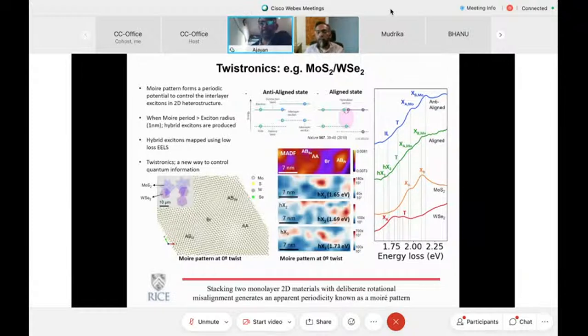And again, these are very difficult to characterize sometimes because, first of all, you need to have single crystal layers to understand how exactly these things go. And secondly, the techniques that are used are mostly transport. So the actual structure property correlation is kind of difficult to come by. We have done, recently, some low-loss electron energy loss spectroscopy (EELS) studies to understand how the electronic structure changes with twist angle. But it seems to be a realistic phenomenon that appears in these kind of monolayer systems when you put them together.